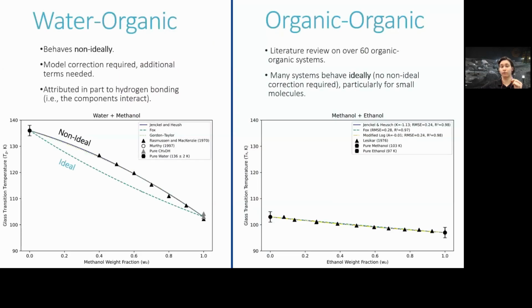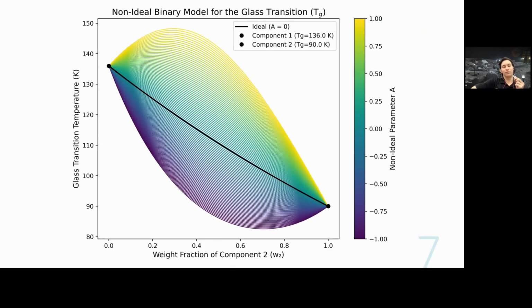So this simplifies things considerably such that, next slide, we can construct a parameter space, conceptualize how these systems might work. Whereas you have water with a glass transition at 136 Kelvin, and then some organic component, perhaps with a glass transition at 90 Kelvin. Then you can imagine either an ideal mixing along the black line or hydrogen bonding that pushes it above the ideal mixing over by the yellow curves, or perhaps some other kind of thinning behavior that might break the glass forming network and push it below. We have competing behaviors, one between the two glass transitions compositions, and then also how they might interact.